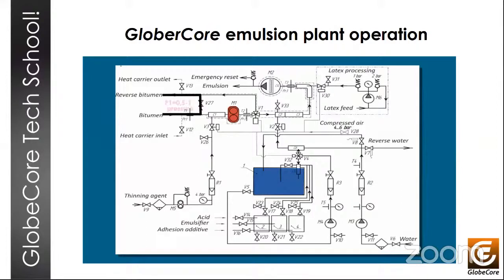Then when the temperature at point T1 reaches 140 Celsius, the bitumen pump M1 is turned on, the V27 valve closes to a pressure of 0.5 to 1 bar, and bitumen starts circulating along a big loop and goes back to the boiler again. When the temperature at point T2 reaches 140 degrees Celsius, the operator selects auto operation mode.